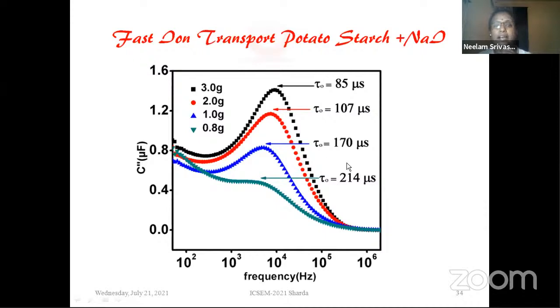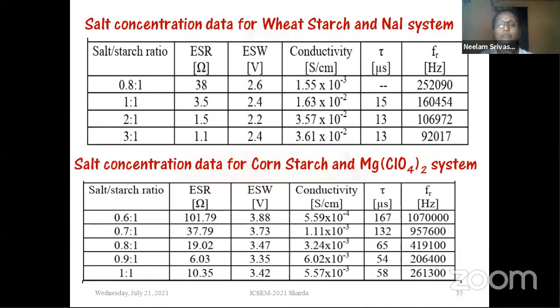This is the fast ion transport. We have measured the ion relaxation time by plotting the imaginary capacitance with respect to frequency, and we found that all these are in the range of microseconds. As the salt concentration is increasing, this ion relaxation time is also decreasing, because the better the ion clusters are throughout the matrix, the easier the ion transport will be. So faster ion transport is being observed. So this is also very good.